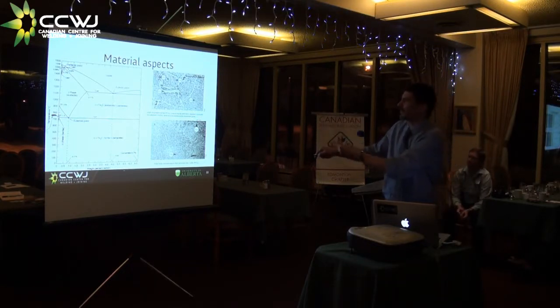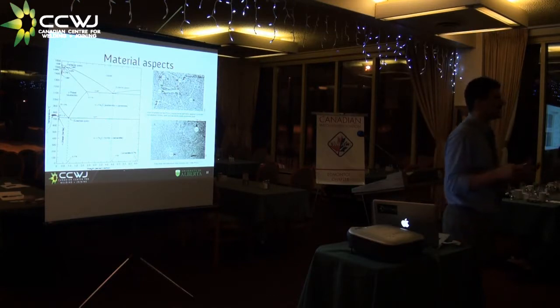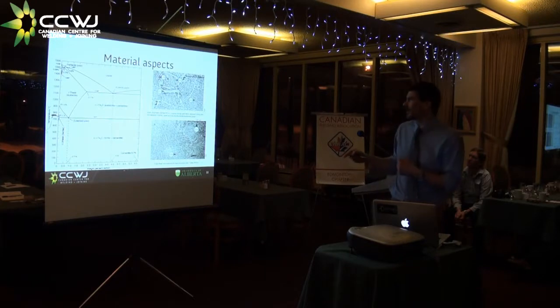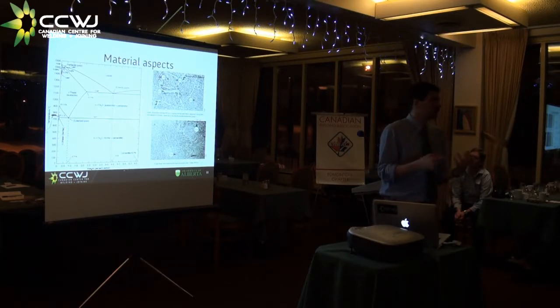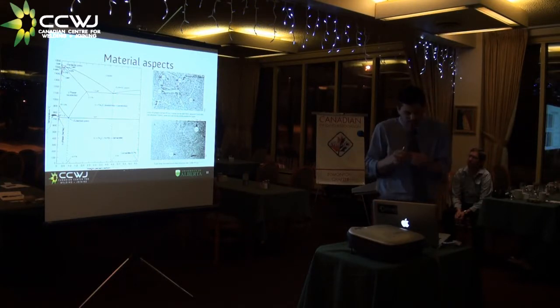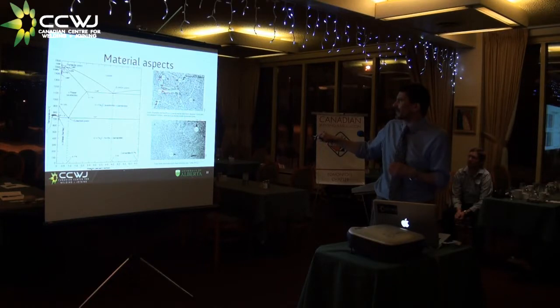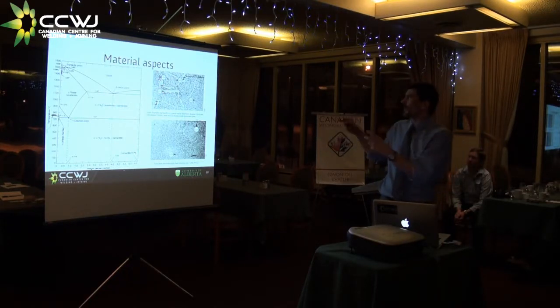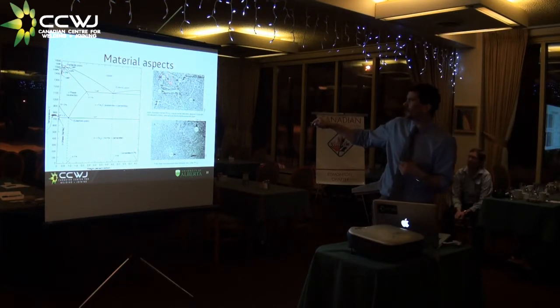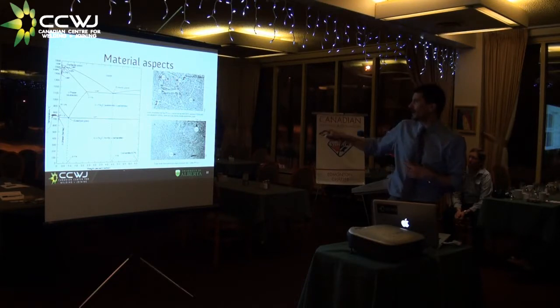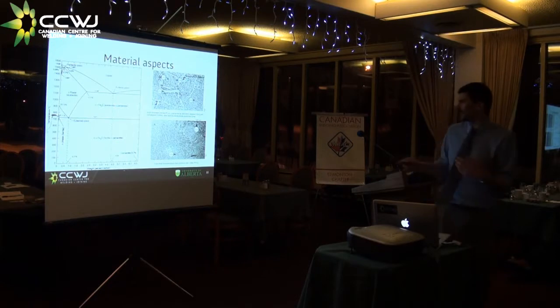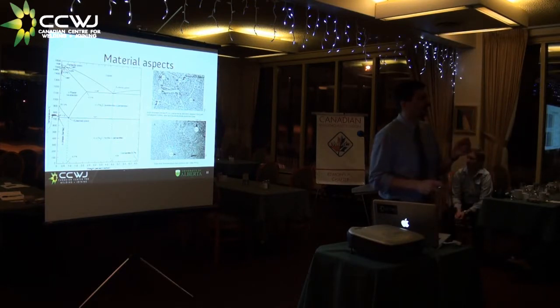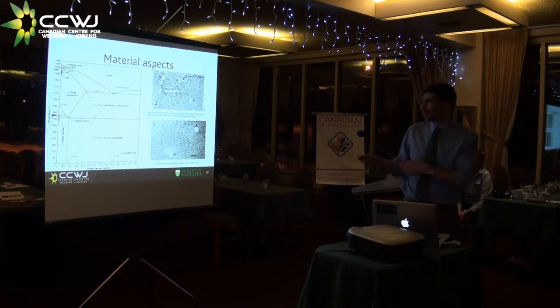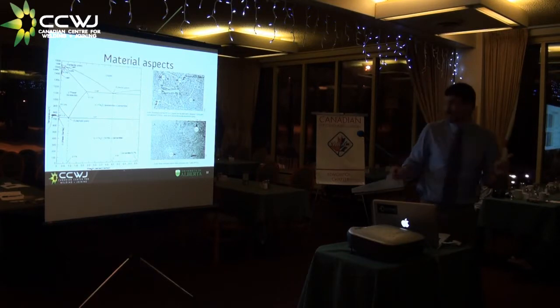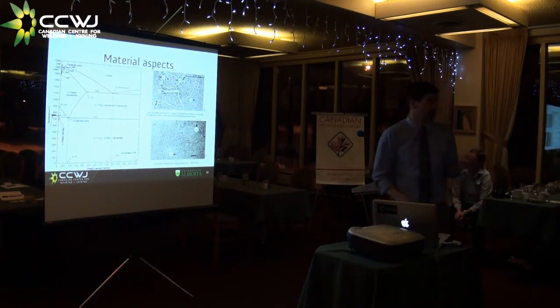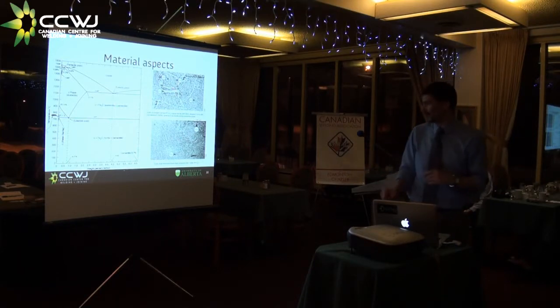So here's an iron carbon phase diagram, and of course, steel in practice has much more than just carbon, right? But this steel or any other material, if you look at it in the microscope, it's going to have what we call a microstructure, with things like primary ferrite on the austenite grain boundaries, or this bainitic structure we call FSA or FSNA, intragranular acicular ferrite, so many things, right? All of these live in a steel of exactly the same composition. The same steel, depending how you weld it, is going to have this or that. Now let me tell you, it doesn't take a PhD to tell that toughness or strength in these two is going to be very different. By the way, this is going to be way tougher than that.